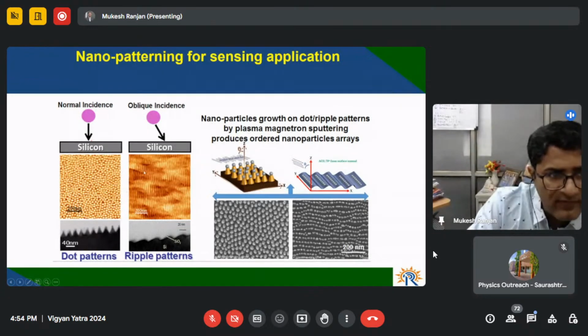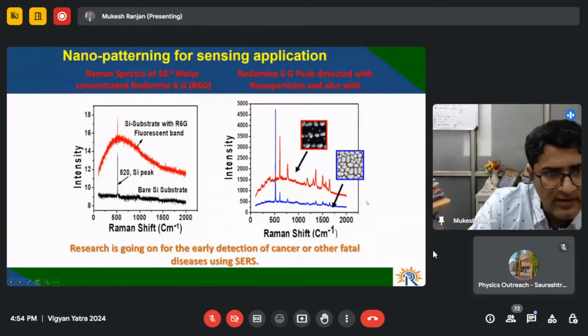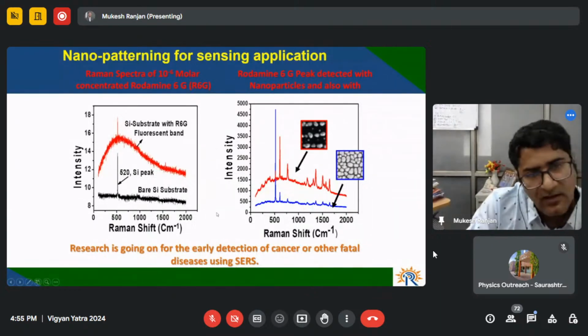So if you pattern your surface with plasma processing, you can use it as a template to make nice chains of nanoparticles. Once they are nicely arranged, they have unique properties as compared to randomly grown nanoparticles. So I'm going to show you an example. We have developed a technology based on the combination of nanopatterning and nanoparticle growth. It is a very highly sensitive Raman sensor.